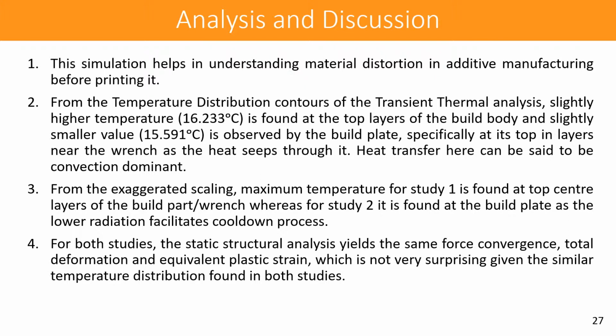From the exaggerated scaling, maximum temperature for study 1 is found at the top center layers of the build part, whereas for study 2 it is found at the build plate as the lower radiation facilitates faster cooling. For both studies, the static structural analysis yields the same force convergence, total deformation, and plastic strain, which is not very surprising given the similar temperature distribution found in both studies.